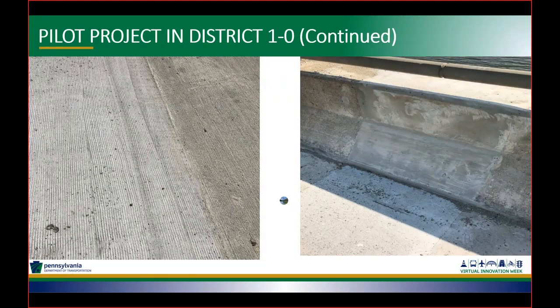Here's the close-up photos of the completed link slab. The photograph on the left, I tried to hold the camera as close as I could, but still get a big picture look of what's going on there. On the right, you see that darker gray color. That's actually the latex overlay of the adjoining deck. And then to the left, the lighter material is actually the UHPC. As you can see, there's a pretty tight joint between the two. We didn't really get a crack or an opening per se. It seemed like it sealed pretty well and joined to the latex.